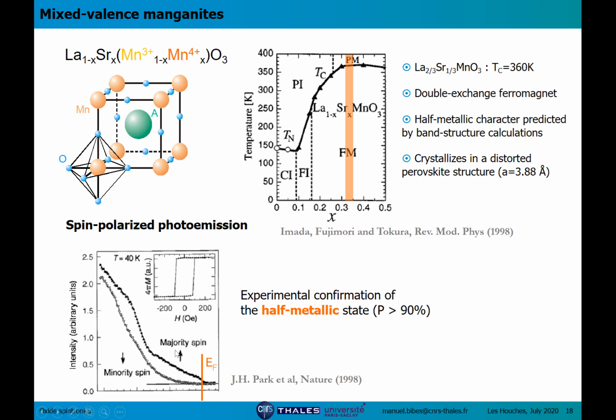So this is the spin polarized photoemission work I was telling you about before. This work from 1998 showed that there was a finite signal for spin up and zero signal for spin down, meaning that the compound was half metallic.